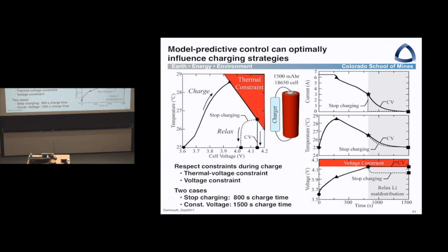So what happens in these two scenarios is that the controller up to this point basically follows the same trajectory. Then what happens here is that the voltage is measured based upon the lithium at the peripheries of the electrodes. In other words, the charge transfer chemistry doesn't know about where the lithium is within particles. It only knows what the surface is because that's what drives the charge transfer chemistry. So what happens here, if I stop charging at this point, then the lithium continues to diffuse into the interior of the particles. So you think you're fully charged here in this fast charging. You think you're fully charged here, but you're not. The peripheries of the electrodes are fully charged, but the battery itself is not fully charged.